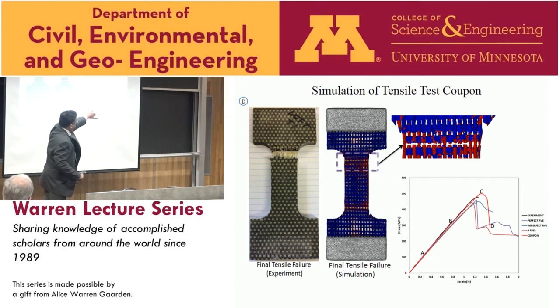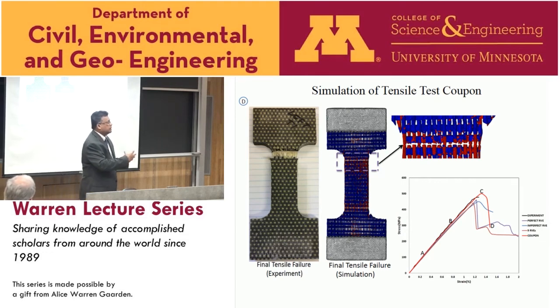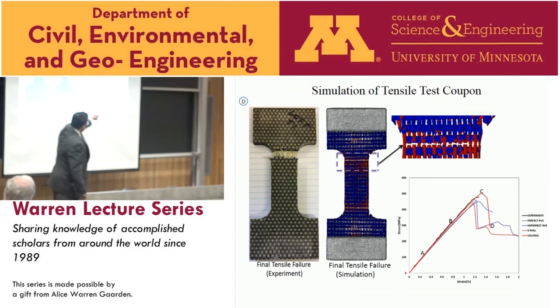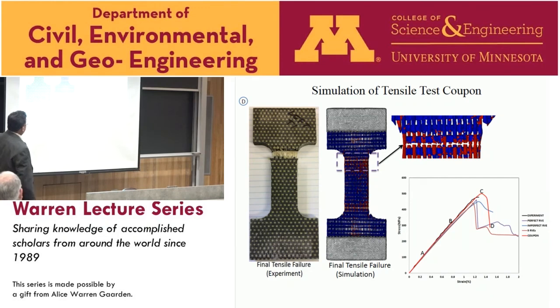And then we did a 9 RVE, because remember, in damage and failure, the notion of an RVE is not just the geometric representative volume element, right? It's the physics representative volume element. Is your volume element able to capture the mechanisms that you want to capture? If you do it just based on geometry, you'll miss the boat, because that's just a geometrical representation. Physics, especially when there's localization, you need to have a correct number of RVEs to capture that mechanics. So that's the middle 3. The entire coupon simulation is that other red curve. You can see it does a fairly good job of capturing what we saw in the tensile test.